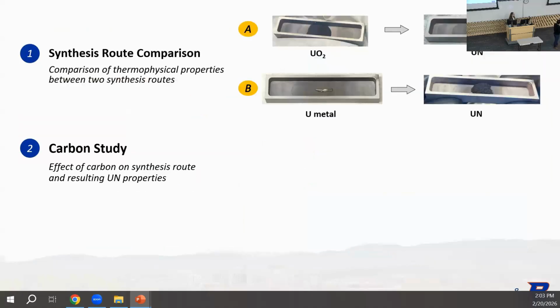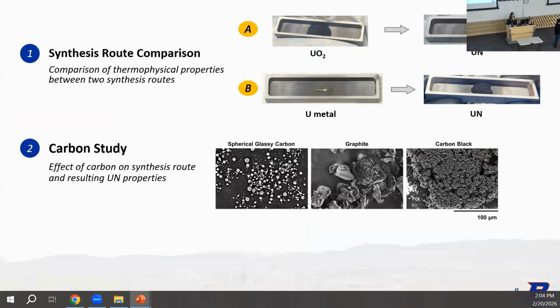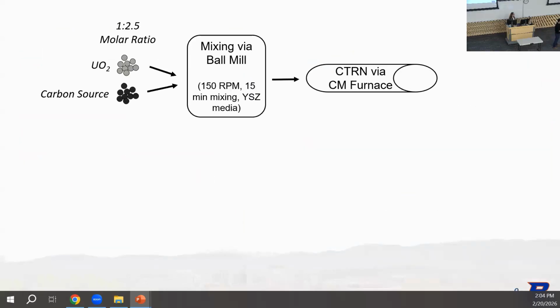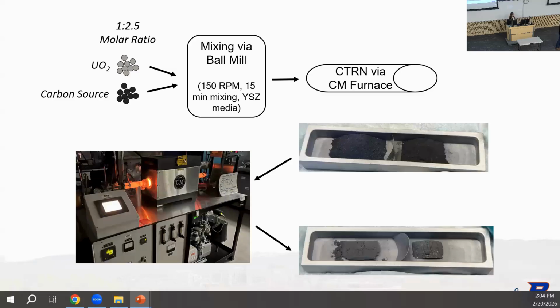So zooming out, if you remember synthesis route A, and I said we introduced carbon into that, we're interested in the effect of the carbon on that synthesis route and the resulting properties of the UN there. In this study, we have 3 different carbon sources that all have varying amounts of crystallinity or particle size as well. This gives you a little bit closer look at that synthesis route. We are mixing carbon into the UO2. This gets mixed with the ball mill, put into the furnace, and then we follow a profile at high temperature, and we go from this, where we have 1 carbon source plus the UO2, to another carbon source. In this comparative study, we've put these both in, and then we got these resulting differences in the UN. So this study is looking at the differences between these 2.